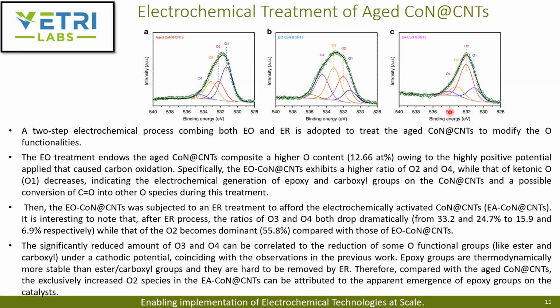The significantly reduced amount of O3 and O4 could be correlated to the reduction of some oxygen functional groups like ester and carboxyl under the cathodic potential that we are applying, which coincides with their observations in their previous work. Also, the epoxy groups are thermodynamically more stable than the ester or carboxyl groups, and they are hard to be removed by electrochemical reduction. Therefore, compared with the aged cobalt nitrogen co-doped CNTs, the exclusively increased oxygen species in this electrochemically activated Co-N CNTs can be attributed to the presence of epoxy groups on the catalyst.